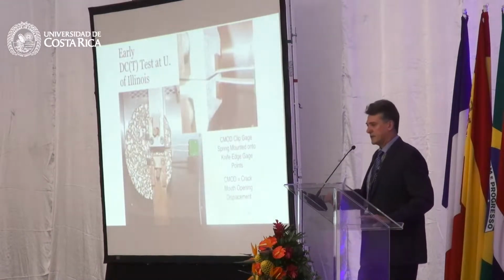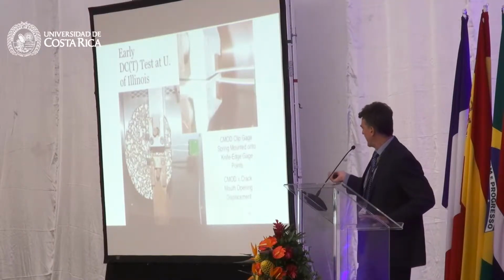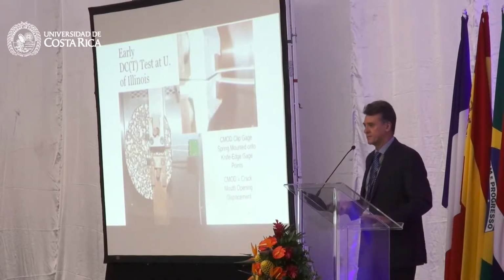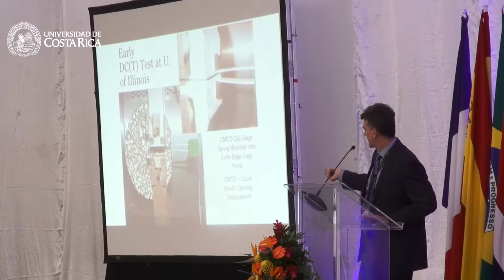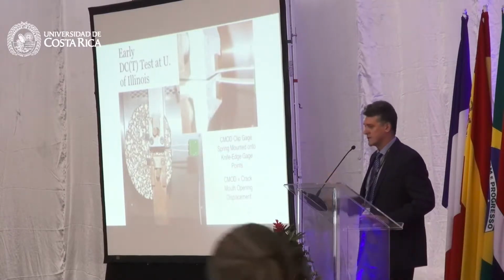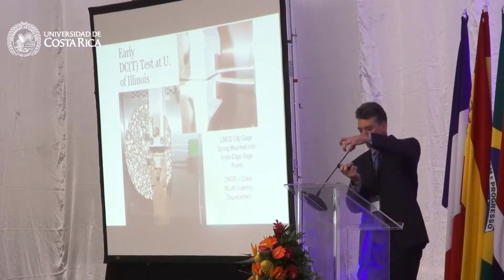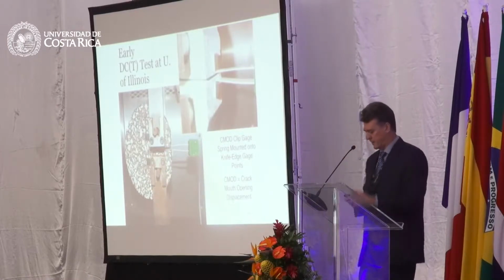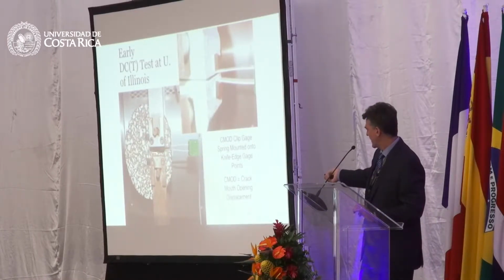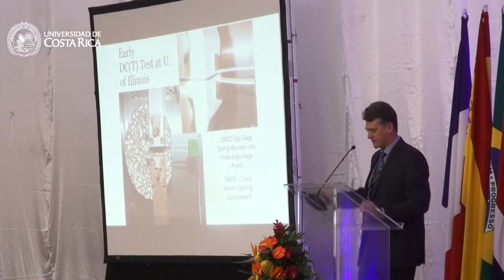Once you get the specimen fabricated into the proper shape, it's a pretty simple test where you put steel bars through the holes you've created, one fixed and one moving, and you pull the specimen apart, and that propagates a crack from the notch across the specimen.